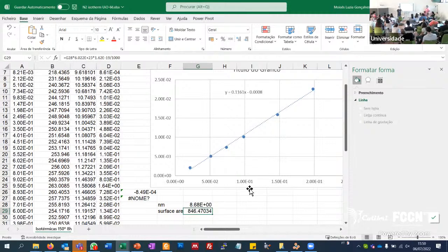Yeah. So one important thing is to remember that this value has an error out of the fitting of the curve, and of course this is the statistical error, but you have another error which is the error of the measurement. If you have like 800 square meters per gram, and you compare with another batch, you make the synthesis and measure it again and find 810 or 820, what it really means is that you have essentially the same material. You don't have sufficient accuracy to distinguish these small details.